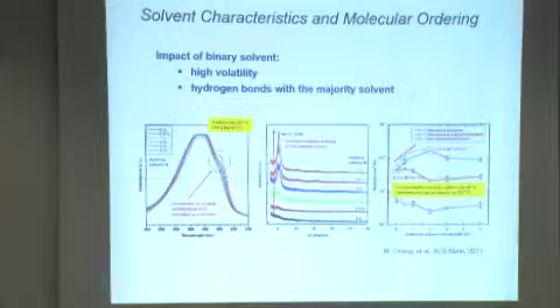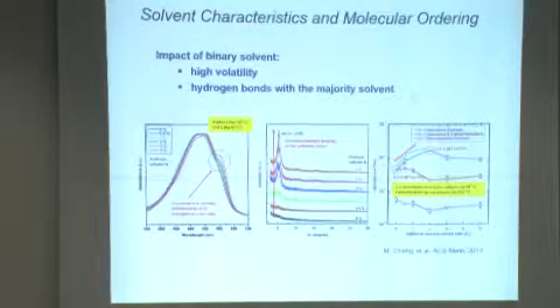All right, so we started off looking at a binary solvent that has high volatility and that may be able to hydrogen bond with the majority solvent. And what we saw is that specifically for adding a little bit of acetone to chloroform as a solvent mixture, as we add acetone, we start to see the fine structure vibronic bands in the solid state spectrum. We see an increase in crystallinity of the films that are deposited from that sample. And depending on the choice of solvent, we can see an improvement in mobility or either no effect or a deterioration in the performance.